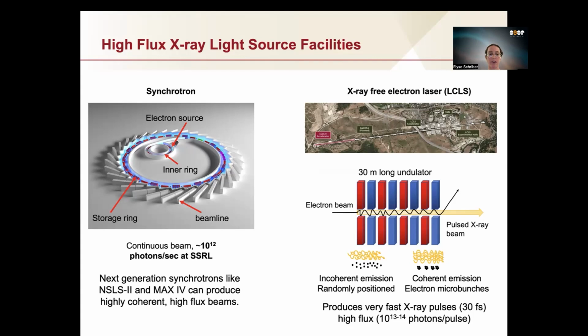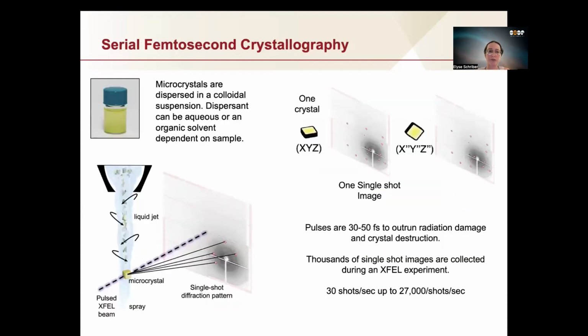So rather than having 10 to the 12 photons per second, you have 10 to the 13 or 10 to the 14 photons per 30 femtoseconds. So you're able to deliver X-rays to a crystal much faster and much more X-rays that are tightly bunched. So the XFEL is exponentially higher in terms of photon flux, and that's really important when you're trying to work with these suboptimal crystals. So biologists realized that there was a great use case for an X-ray free electron laser when they developed the technique serial femtosecond crystallography.